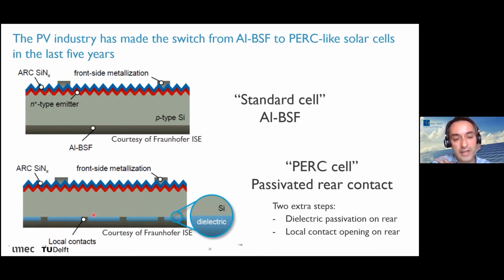We put this blue layer in between. This is a dielectric passivation layer. And we open the blue layer in certain locations because we still need to make contact holes. We need to have some contacts between the aluminium and the silicon.